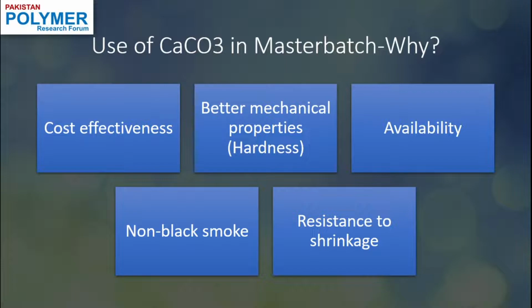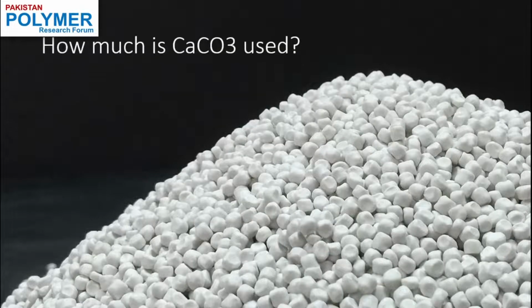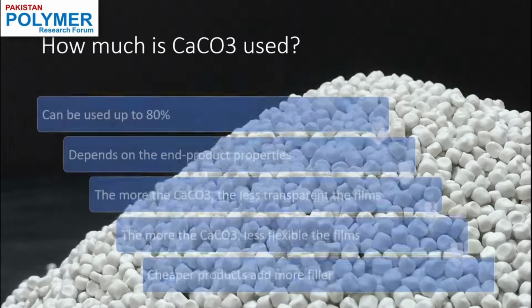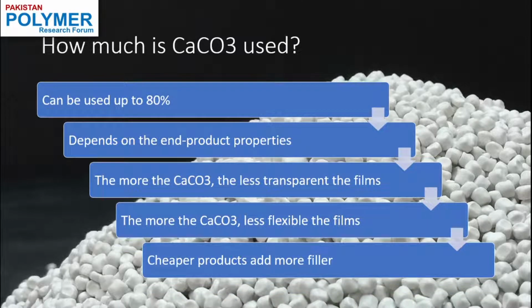Calcium carbonate is being used in the manufacturing of polymer master batch, and how much should it be used? The amount of calcium carbonate that can be used is up to 80%. It totally depends on the end product properties that you are striving to achieve. The more calcium carbonate you use, the less transparent films you'll get, because transparency is a property you achieve by using the polymers, especially LDPE, and it's not a property of the calcium carbonate filler. So the more calcium carbonate filler you use in your master batch, the less transparent and the more whitish and opaque films you'll get.